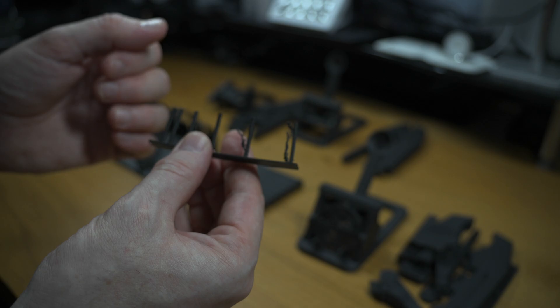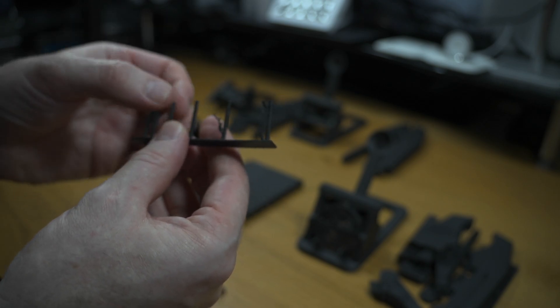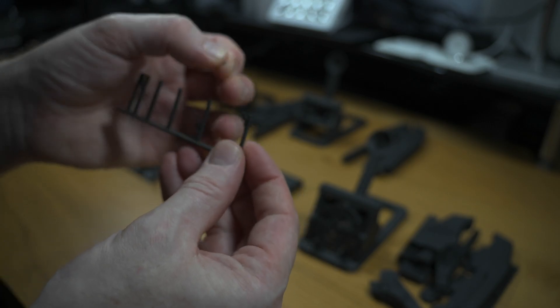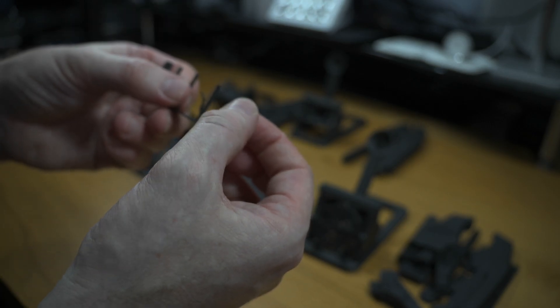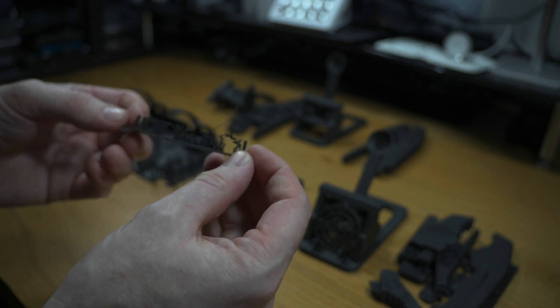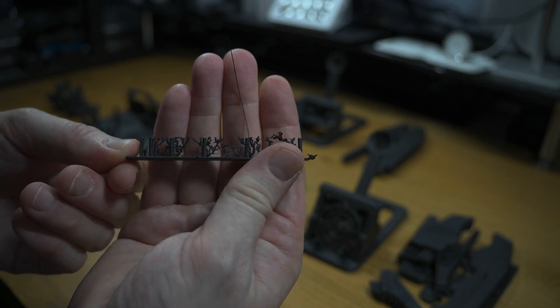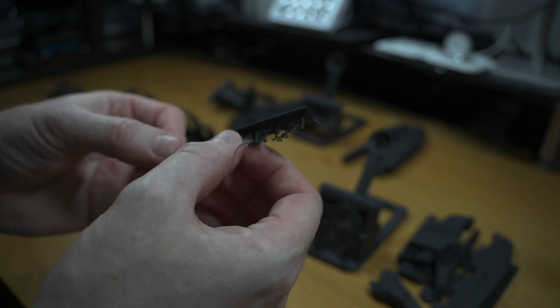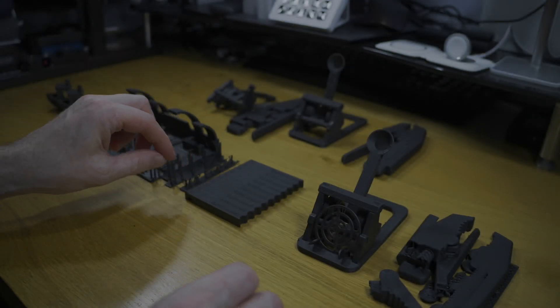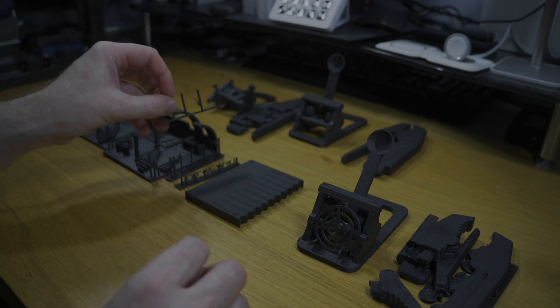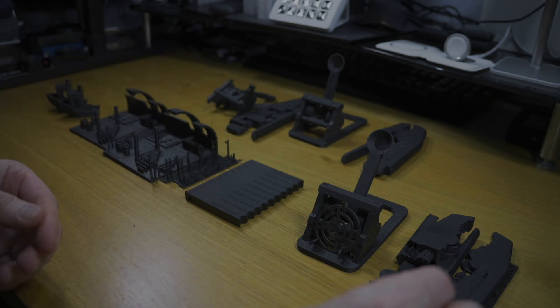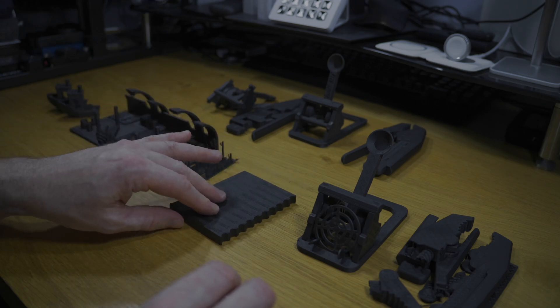This is the default setting which is provided on the profile from eSun, which is 30 millimeters per second. While we still are getting stringing, I mean stringing can always be removed, the actual poles themselves are pretty good. Then I moved to 40 millimeter per second retraction and it's a mess. So what I can say is that the default set by eSun in their profile, 30 millimeters per second, is perfect and that's the setting to leave it at. There is a little bit of stringing but nothing to get upset about.